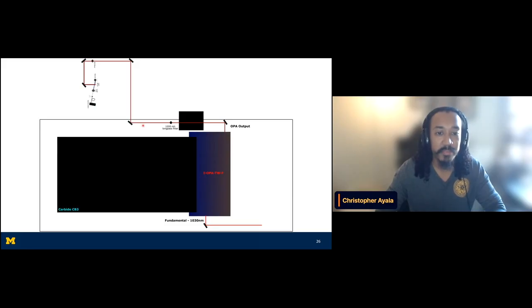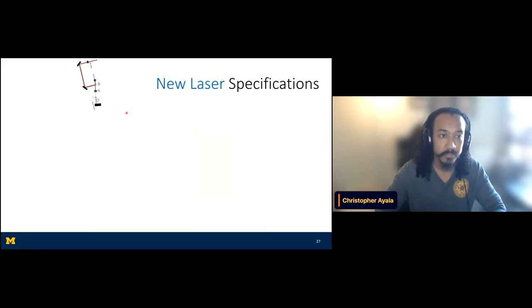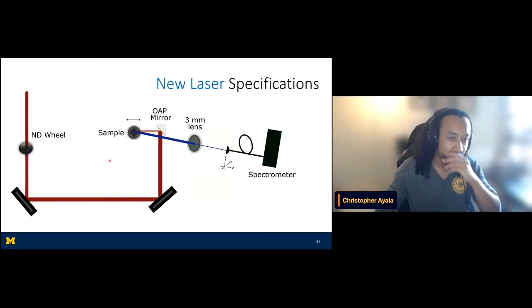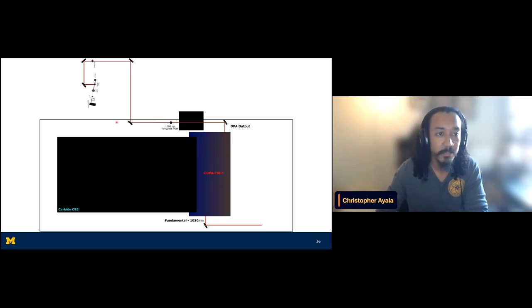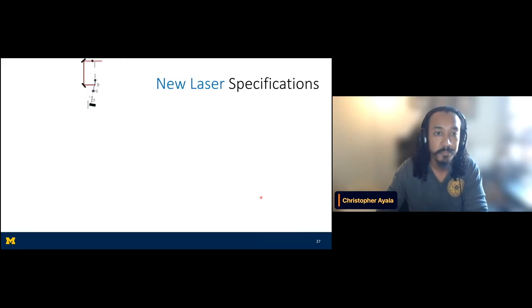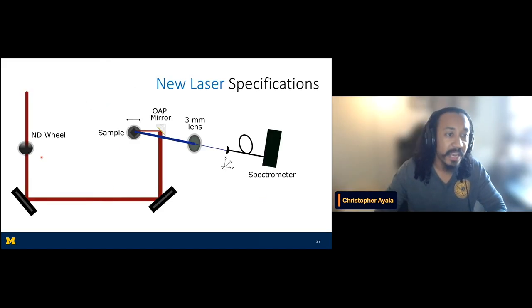So we take the output from this very nice new laser that we have here, and I give you guys a close-up of what our experimental setup looks like in ambient, keeping in mind that this whole experimental setup takes maybe a quarter of the space that a gas chamber and gas phase harmonic might produce for you. We have, importantly, an ND wheel, which allows us to attenuate and choose how much pulse energy we are putting onto the sample. We have an OAP, an off-axis parabolic mirror, to focus it tightly onto the sample, and the light then gets sent through a lens to focus onto our spectrometer.